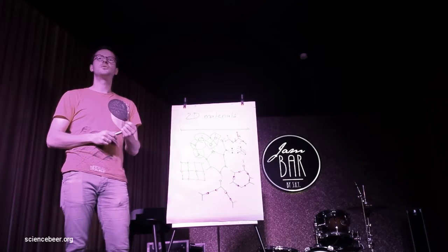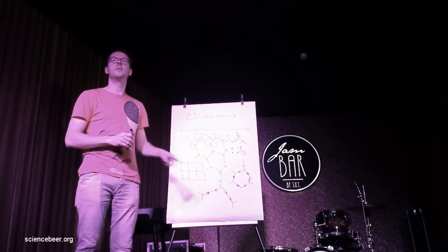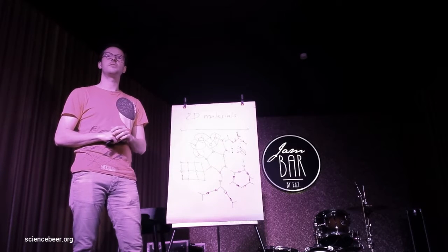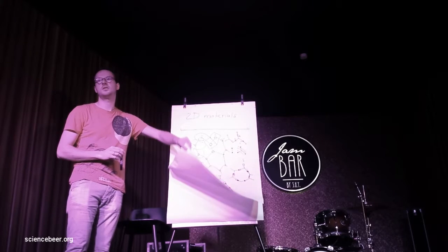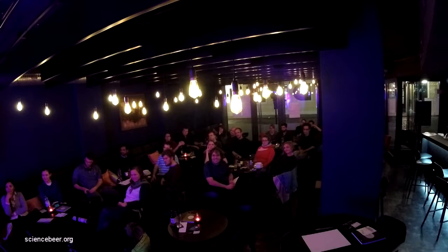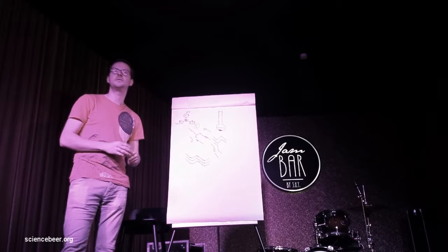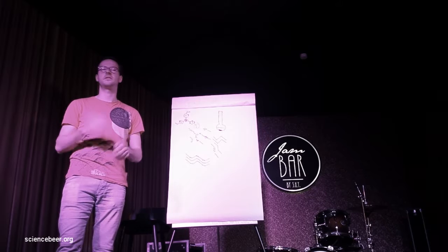We don't have control in this particular reaction at this place, but we have control regarding solvents, temperature, and reaction time in which the reaction takes place. When you heat it too much, you won't get a result. Or if it's too short, then the crystals are too small, and you will see it, for example, in the characterizations like surface area, that it's much lower.